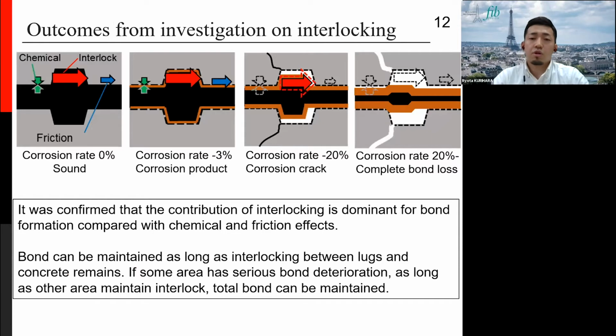This slide shows a summary of outcomes from the investigation of bond deterioration by interlocking loss, as a summary of this research. These figures show the relationship between bond condition and corrosion progress. In the sound condition, the three bond components can work and the interlocking effect is dominant. And under the slight corrosion state, the chemical effect reduces due to the corrosion product gel, but the interlocking and the friction effect can be kept.